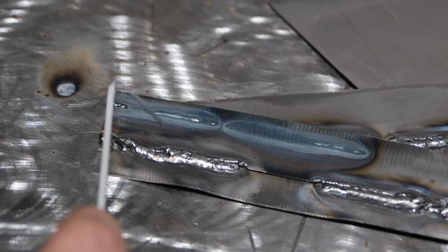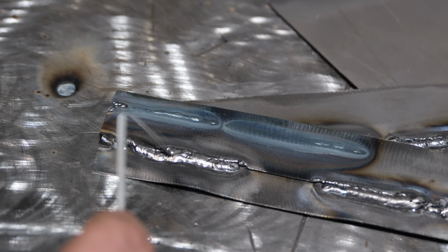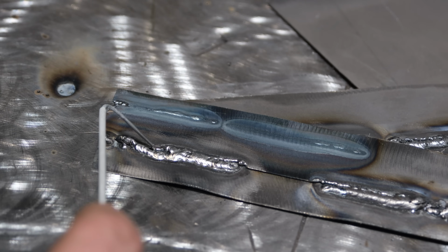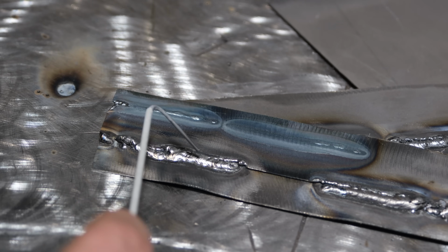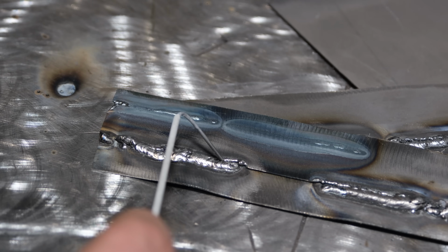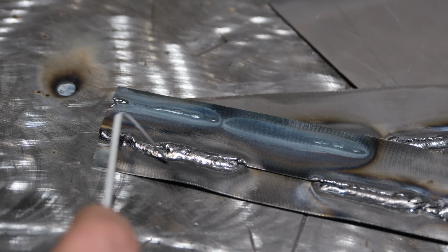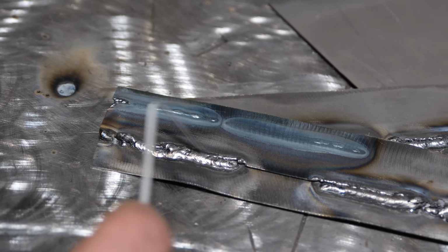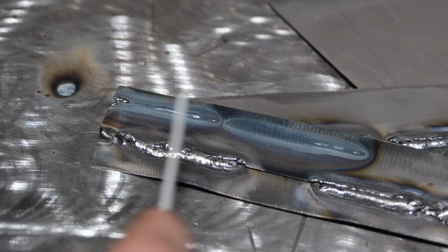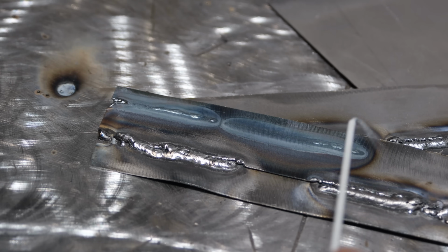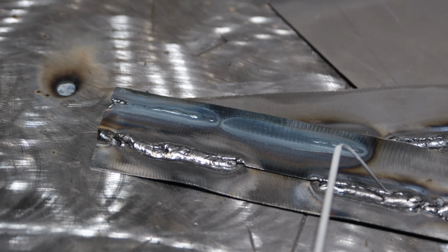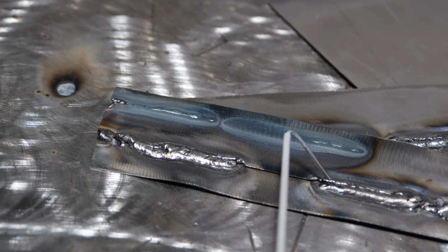I tried boosting amperage, and once again, the 6013 here just did not want to weld. It kept sticking the rod, and I would just blow through the edge of the plate. I mean, this was a no-go. So 30 amps is roughly what this was at. That's no bueno. Over here with the 6011 at about 30 amps, it ran easier.